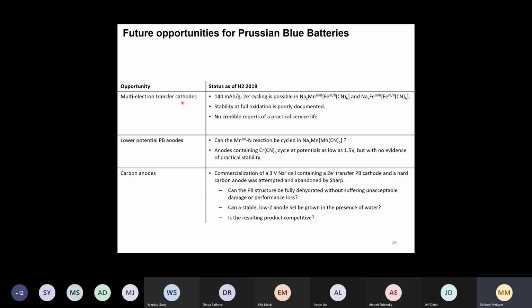And, you know, we had about 70 milliampere hours per gram specific capacity out of these materials. But you could really achieve something on the order of 140 milliampere hours per gram if you could have 2 electrons per formula unit, or 2 sodiums inserted per formula unit. But of course, that would require that you have 2 redox active centers that change their oxidation state by 1. So it can be done in something like manganese iron. It could not be done, for example, in nickel. I think nickel would always stay at 2+ oxidation state.